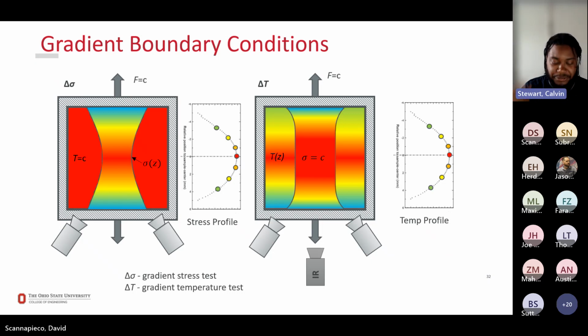So another really interesting demonstrator that we are working on in my group is this idea of gradient boundary condition testing. To be able to test a material in parallel, to get more than one curve of data out of a single sample. Two concepts that we've proposed is this idea of the delta sigma and the delta T test. In the delta sigma test, you have a geometry that's non-uniform, so that when you test that sample and you pick points along that geometry, each point has a different value of stress. If load is constant, as you change the cross-section, stress changes. And if you carefully contour that shape, you can minimize triaxial stresses that could develop, right? You can also minimize how much stress concentration you have.